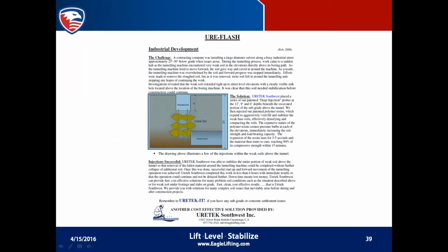Operations were being done up in Canada by URETEK, where a contracting company was installing a large diameter culvert along an industrial street approximately 25 feet below grade. During their excavations, they hit pocket voids, which caused a collapse of the soil, which actually got their excavator stuck underground 25 feet. So some testing was done at the surface, and they found where all of the loose soil and pocket voids were located.